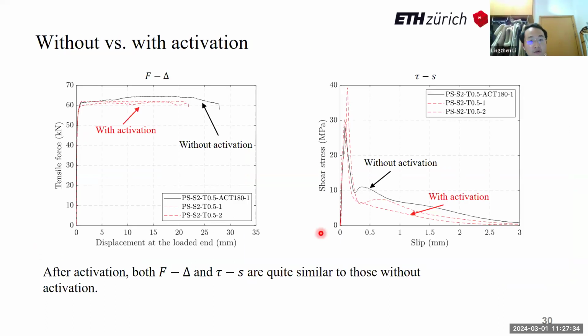After some analysis and post-processing, I found that for global force-displacement behavior, the curves for joints without activation or with temperature activation are very similar. Similarly, when I looked into the local bond slip behavior, I found that the behaviors without activation or with heating activation are very similar. This suggests that we could use the bond behavior or joint behavior without activation to represent those with activation. This would help us simplify the testing procedure and the analysis procedure.